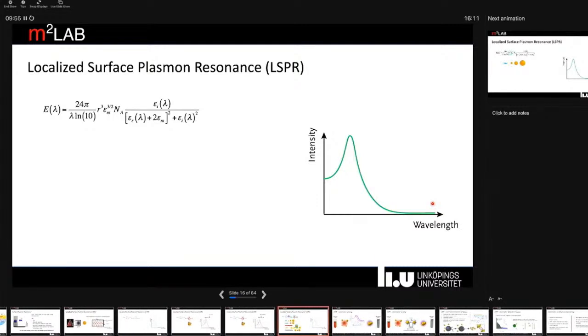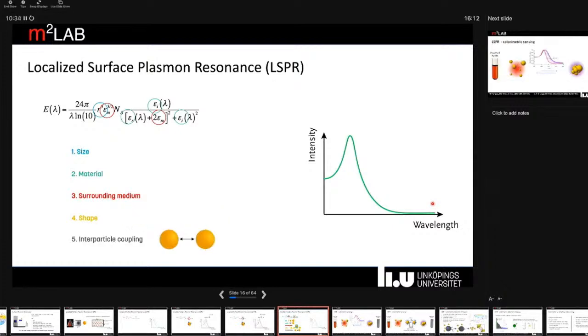We can also look at what other aspects in the metal nanostructures influence the optical properties, or sensor performance, of sensors based on LSPR. And one such factor is the size of the particles, and that influences the LSPR band quite a lot. And of course, also the dielectric function of the metals used, so the materials essentially. I already mentioned the surrounding medium, and of course, also the shape of the nanoparticles that we're using, or the nanostructures, and also how closely they are spaced, if we get optical coupling between the particles.